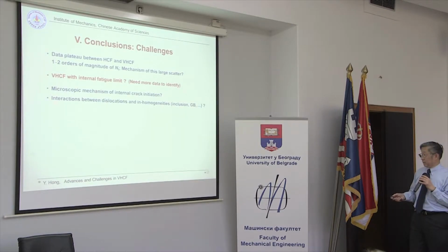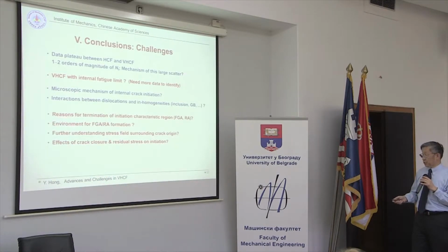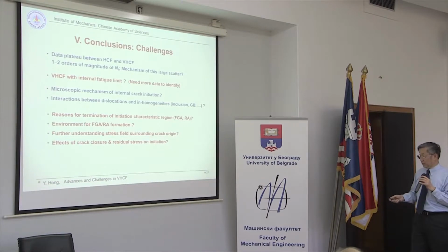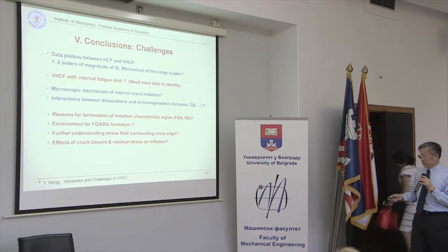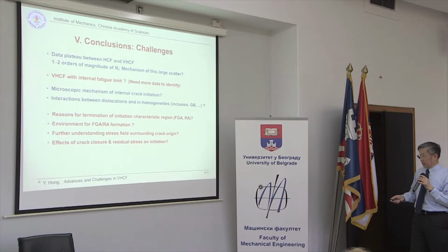And the third and fourth, we may ask what is the microscopic mechanism of internal crack initiation, and how about the interactions between dislocations and inhomogeneities, like inclusions and grain boundaries. And also, what's the reason for termination of the initiation characteristic region? And also, what is the environment for this initiation region formation? We need more data to identify these points, and also we should do some extra experiments to reveal the stress field surrounding the crack origin, and also the effect of crack closure and residual stress on initiation.